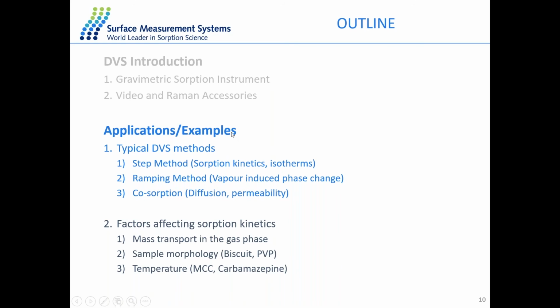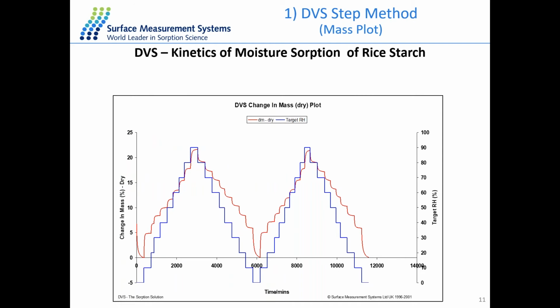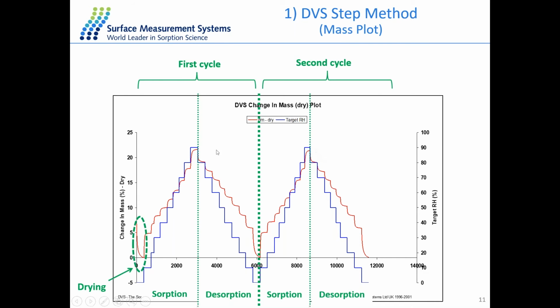Then I would like to go through some different methods we can perform in the DVS system. The first, very typical method is the step method, where we change the humidity step by step. Here's an example with a rice starch sample for moisture sorption. We introduce the water vapor at different concentrations and change the relative humidity from 0 to 90% RH in 10% steps. The red line is the change of mass for the rice starch sample. It picks up the moisture without going through any phase change, and the second cycle is exactly the same as the first cycle. That means this moisture sorption and desorption is a perfectly reversible process.